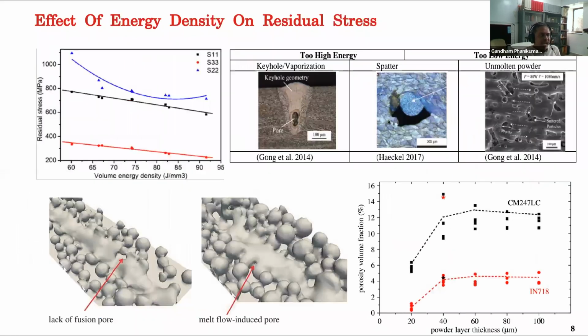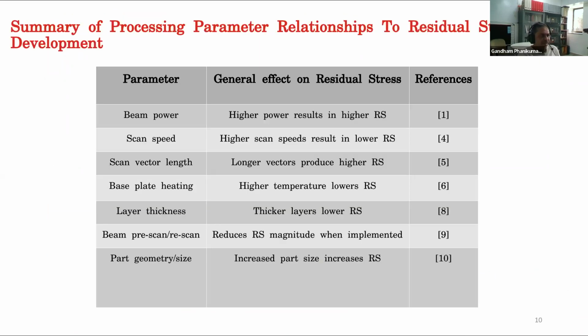And you could also play with the thickness of the layer, and we have also done some studies to show how the individual layer thickness can also play a role in the accumulation of residual stress. And of course, if you don't have the residual stress under control, the choice of energy parameters also can start to aggravate a lot. Okay, so you have these defects that we have talked about earlier in the context of porosity. They will actually be much more aggravated if your residual stresses are slightly high. Okay.